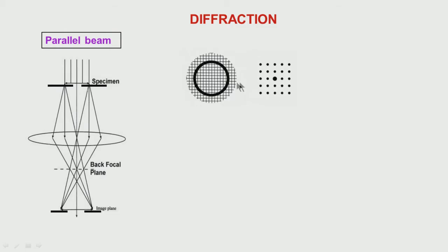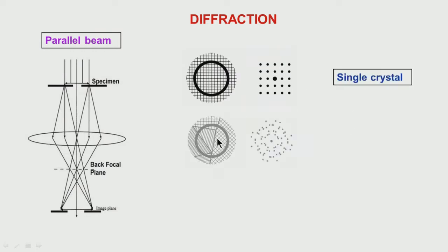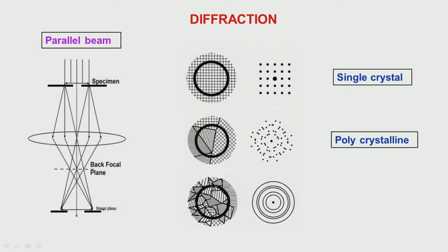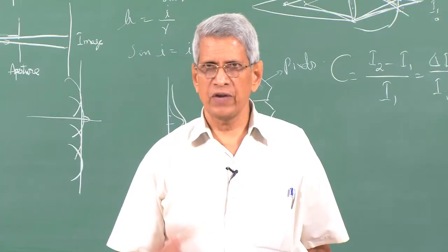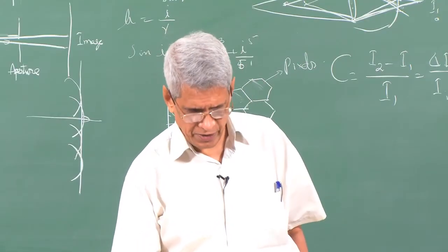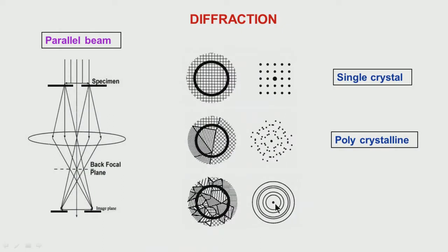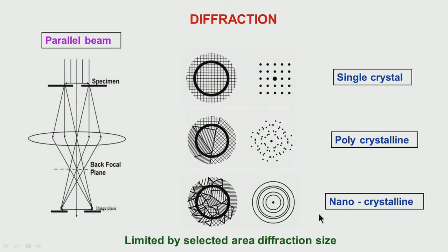Suppose we choose an area which essentially turns out to be one single grain. So from that grain, we can get a single crystal diffraction pattern. Suppose that area which we choose contains more grains. Then the diffraction pattern from each of the grains will come, and this is how a pattern will appear. You can see the complexity which is coming. If the aperture contains a lot of grains with various orientations, we assume all random orientations are possible, then we will essentially get a ring pattern, which is observed for nanocrystalline particles.